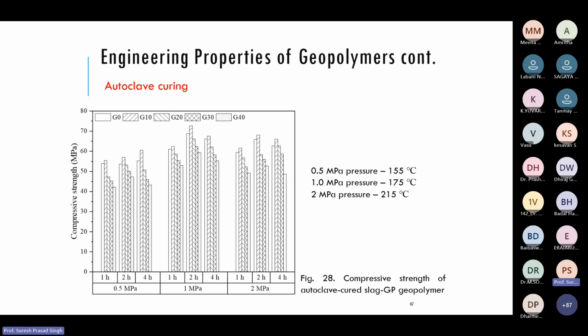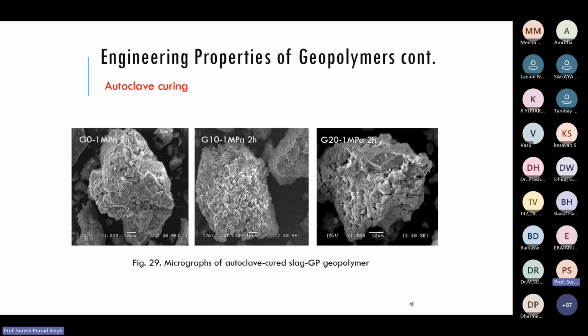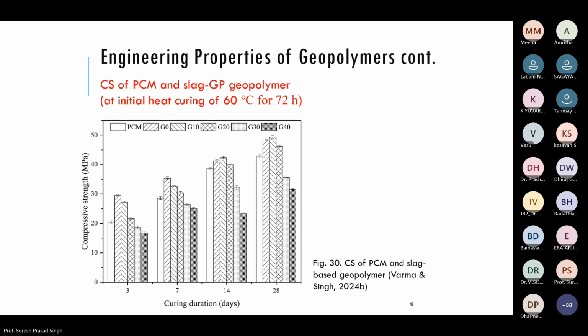So we also conducted curing in these autoclaves, uniform curing. So shrinkage cracks will not be there, uneven curing is not there. You see that solid materials are formed once the autoclave curing is adopted. And this is the initial heat curing of 60 degrees for 72 hours. After that, there is normal curing. Then also we got a very high strength, as high as 50 MPa.